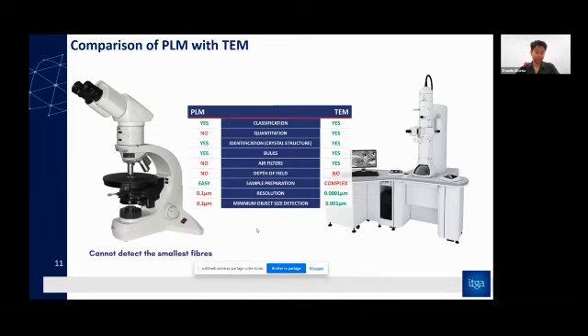Now, if we want to compare the techniques, let's take polarized light microscopy and compare it with TEM. In terms of classification, both of them are able to classify and identify the crystalline nature. However, the problem with PLM is that we cannot quantify, and we are limited by the resolution. So we cannot see the smallest fibers, as Kevin has just mentioned. In that case, we definitely need electron microscopy to be able to see the thin, short fibers and the long thin fibers.